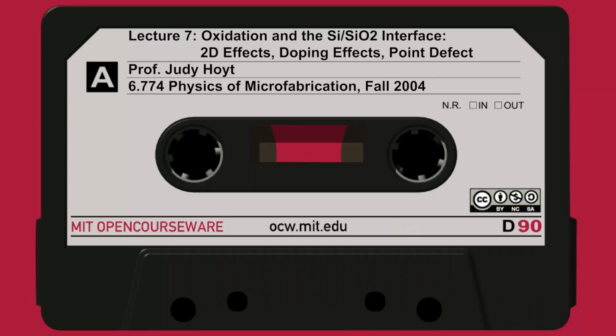And unfortunately, I'm sorry about the colors, but I think you can see this top layer is the original nitride, silicon nitride. Look at the flap. The flap that was along this sidewall has been lifted up because the oxidant has moved its way under there and pushed it up. And then it's sort of quasi-vertical over here. The flap has been pushed out by the oxidant that was coming under here from the left and pushing on it. So the thin flap lifts up during oxidation, but it's still a reasonably flat surface, not perfect, but they're trying to reduce the amount of bird's beak and bird's head that formed.